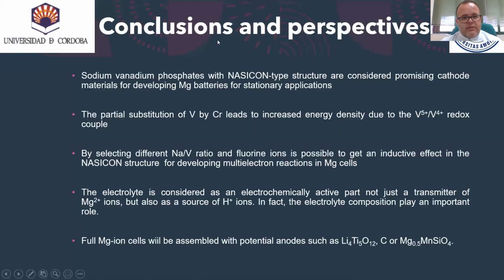As a conclusion, we can see that sodium vanadium phosphates with this NASICON structure are considered promising materials for developing magnesium batteries for stationary application. The partial substitution of vanadium by chromium leads to increased energy density due to the vanadium 5, vanadium 4 redox couple. By selecting different sodium to vanadium ratios and fluorine ions, it's possible to get an inductive effect in the NASICON structure for developing multi-electron reactions in magnesium cells.